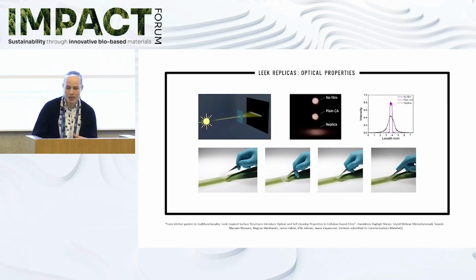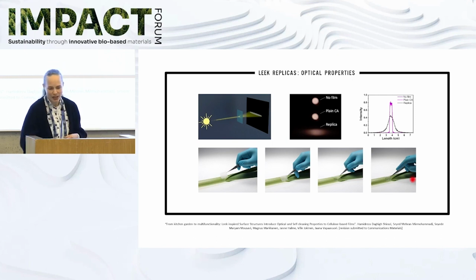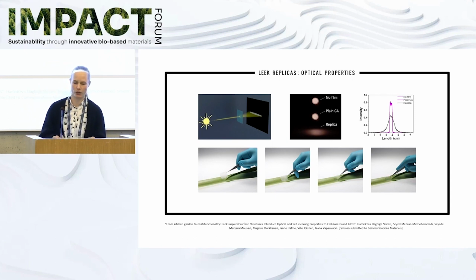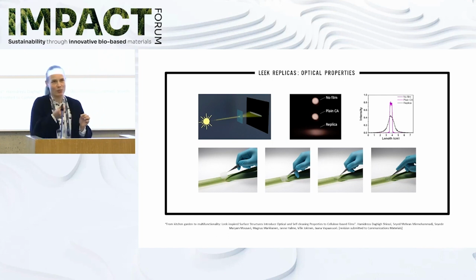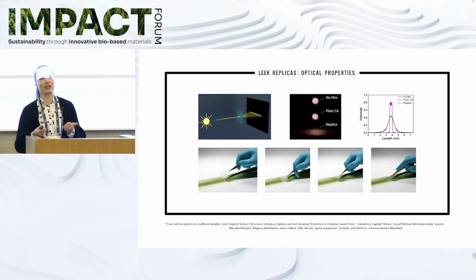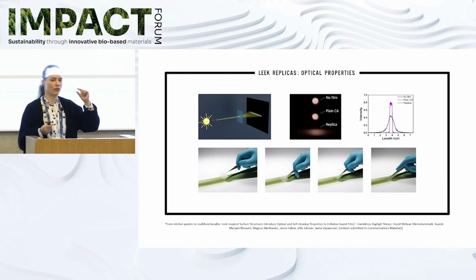You can see them. And as you can see in this photograph here, they are highly transparent, so this was one of the key features that we need for the solar cells. Also, when you keep lifting them from the surface, you can maybe observe that the picture becomes a little bit hazy. So they have this interesting property called diffusive transmittance, and this can also be an advantage when you need to collect a lot of light with a very thin film device.